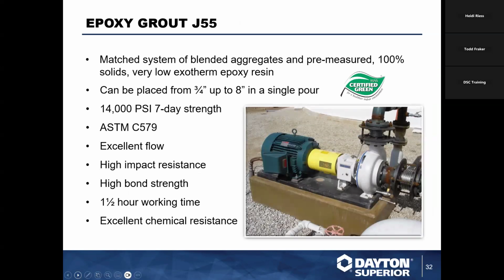All right, epoxy grout, again, has its place, and there's a picture of a nice little machine with a big chunk of epoxy grout underneath it. They can be placed into fairly thick pours. 8 inches is pretty significant. We can hit 14,000 PSI in 7 days. That refers to the ASTM C579 specification. Great flow, great bond strength. Again, it takes vibration and it has excellent chemical resistance, better than a cementitious grout.